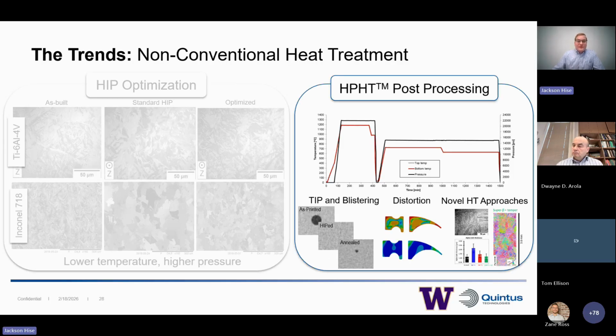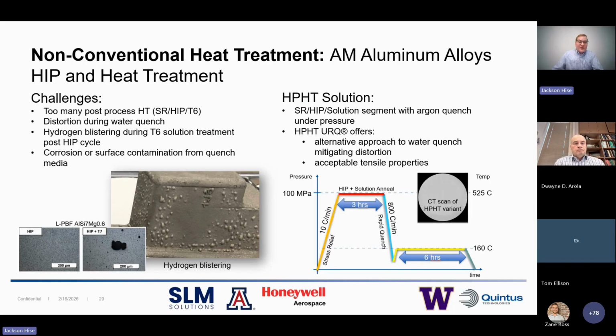One other thing I want to note and discuss is this high-pressure heat treatment post-processing. We know that, especially in AM aluminum alloys in particular, there are many post-process techniques. There's distortion during water quench, and there's hydrogen blistering that occurs. Well, if we do all of this under a pressure medium, we're able to mitigate and avoid quite a few of these challenges. We can do the stress relief, HIP, and solution segment all within a Quintus press and do the quench under this argon medium. This alternate approach avoids water quench distortion and also produces acceptable tensile properties.